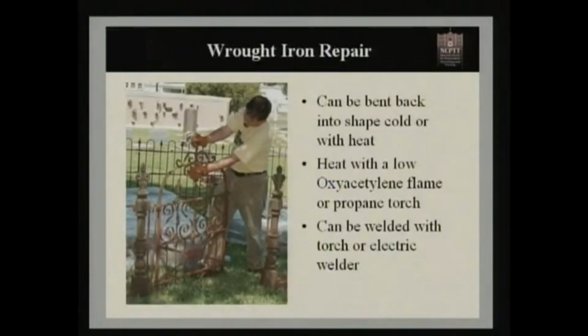A lot of times these finials, pickets, things like that can be bent back into shape. And this can be done cold if it's not a severe bend, or if it's on a small element. If you have a very corroded element or a very severe bend, you might want to heat it up. You can either use an oxyacetylene flame. Be careful that you're not using a cutting torch that could do damage, but oxyacetylene flame or a propane torch. And this should be significant enough to heat it up to anneal the metal to easily bend it back into shape. Any breaks or tears or rips in the iron can also be welded with a torch or electric welder.